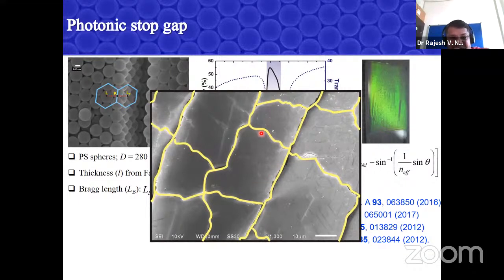What about measuring from this small region? Instead of doing the measurement from this whole region of the sample, let's focus on a small region here, probably a 10 micrometer square area. So that's what we are going to do, and that needs a lot of sophisticated instrumentation development, because no commercial spectrometer will let you measure light from a 10 micrometer region. You need to have your own setups, because in a commercial spectrometer, whatever you use, the beam size is 5 millimeters. So 5 millimeters may be much larger than this image itself. So when you do a conventional measurement like the spectra shown here, you may be mapping thousands of these bits and pieces. So all kinds of ugliness in your samples will come back into your measurements.